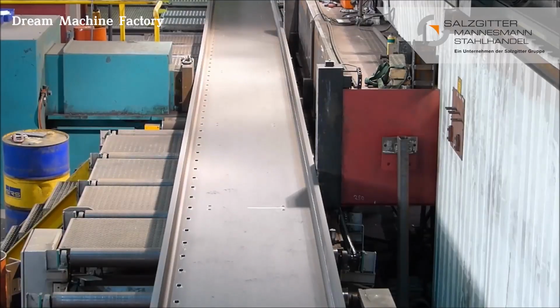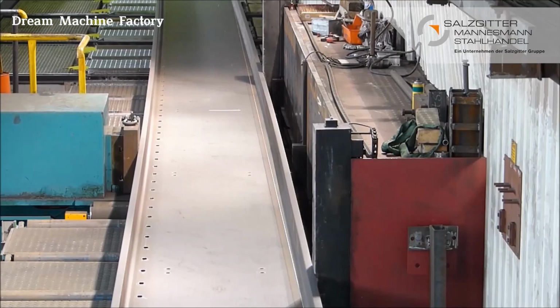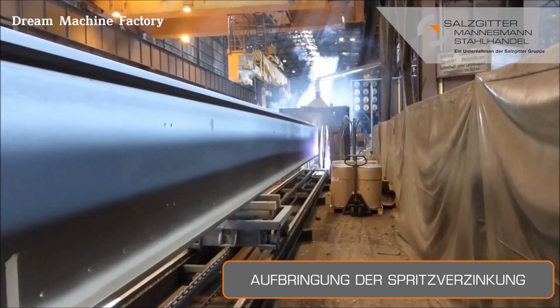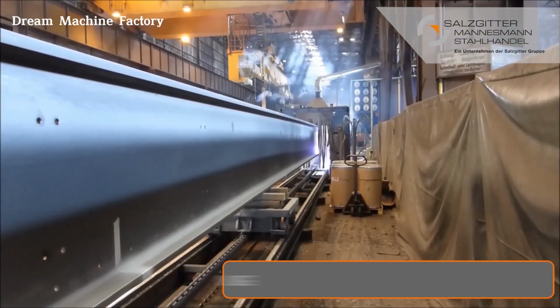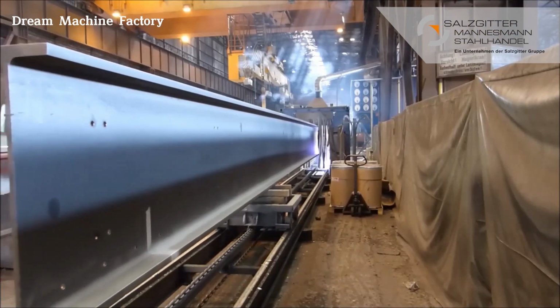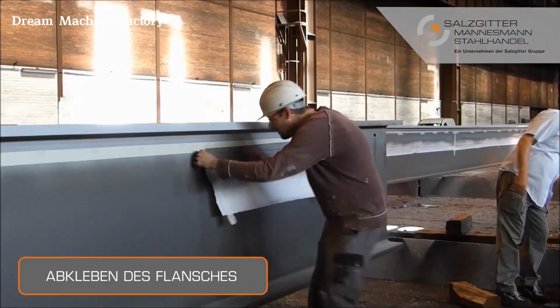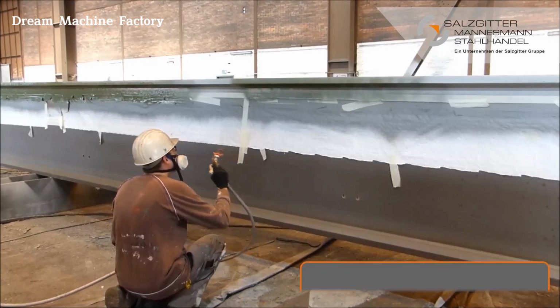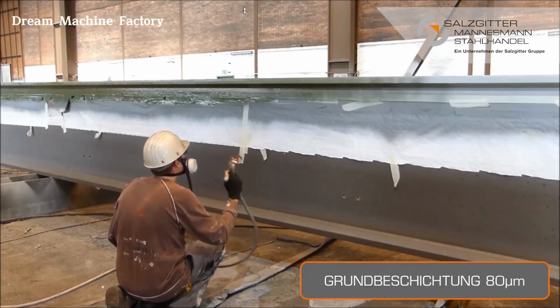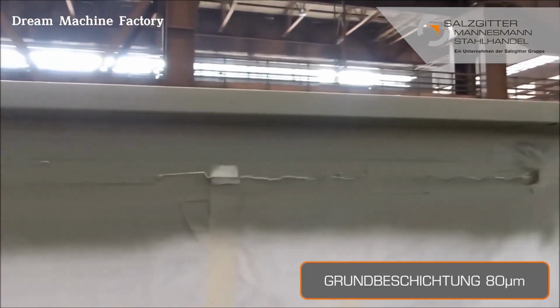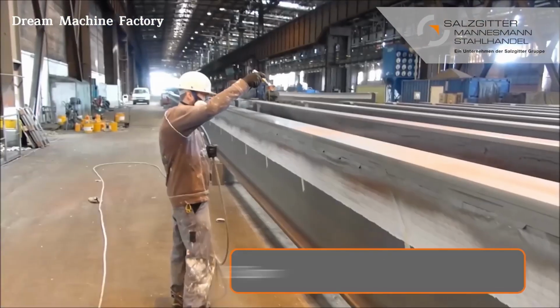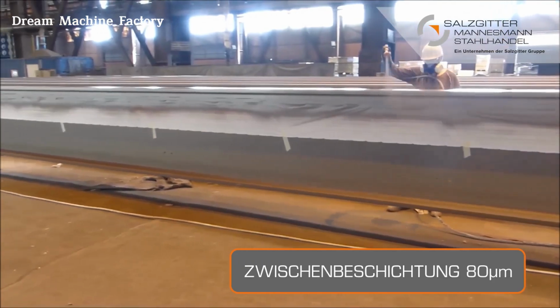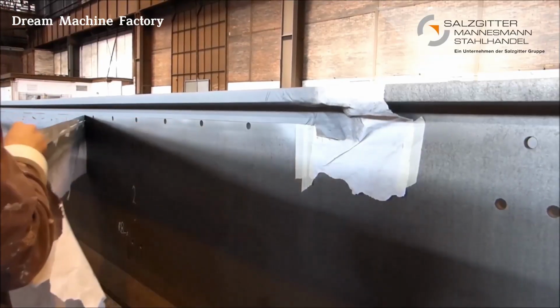The girders are coated using thermal spray galvanization, where molten zinc is sprayed onto the surface to provide long-lasting corrosion protection. Before spraying, the flange areas are carefully masked to prevent coating in specified zones. After galvanizing, a primer coating with a thickness of 80 micrometers is uniformly applied to enhance durability and ensure strong adhesion for any additional protective layers.